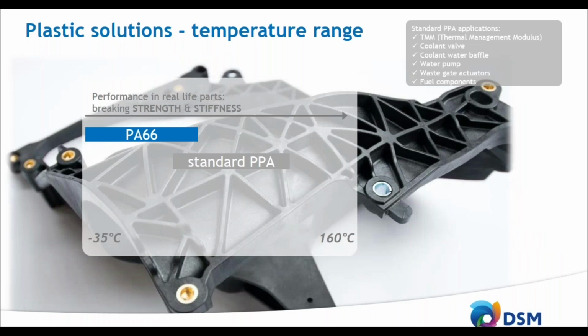So what can you actually do with PPAs? What we see here is, on the horizontal axis, the strength and the stiffness of a part. You can work with a very low temperature up to around 70 degrees C with a polyamide 6,6. After that, you can expand the temperature range with a standard PPA. But those standard PPAs tend to be a bit more brittle at lower temperatures and room temperature. So standard PPAs are normally used in thermal management modules, coolant applications like valves, water baffles, water pumps, and fuel components.